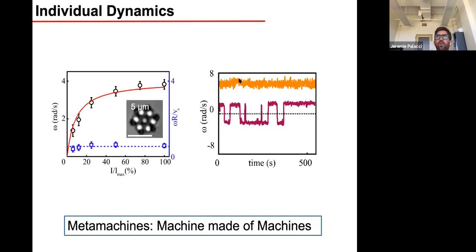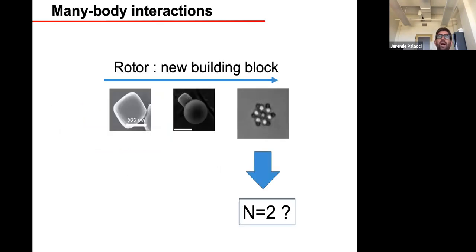So we can control the dynamics of the spinning with the intensity of the light. At high intensity of the light, the movement is persistent. At low intensity of the light, the angular speed is reduced, and the particle can have intermittent reversal of orientation, the statistics of which we're studying right now. I can't tell you much. And so we have this new building block.